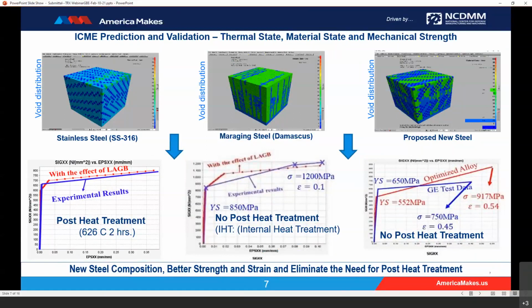This slide presents the predicted stress-strain curve of the GE stainless steel after thermal heat treatment, stress relief at 626 degrees Celsius for 2 hours, of the Maraging Steel (Damascus), which consisted of inherent heat treatment, and the optimized steel option, which does not involve heat treatment.